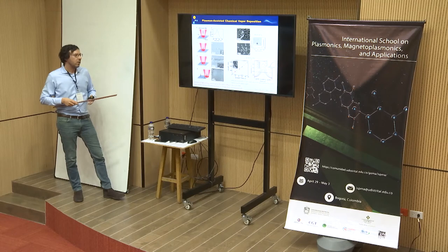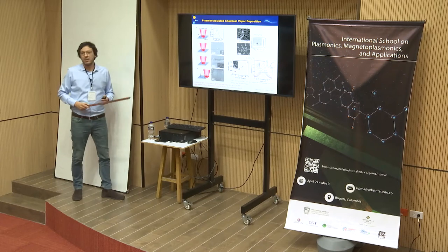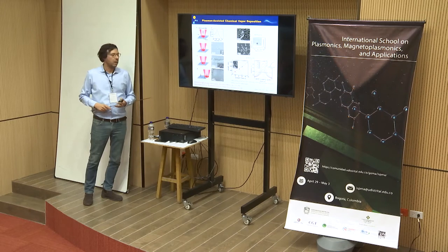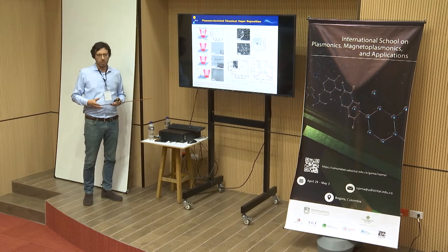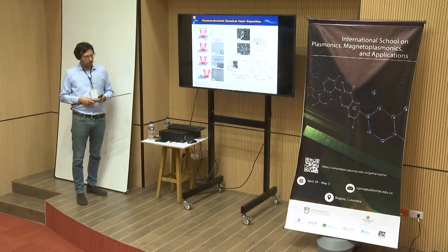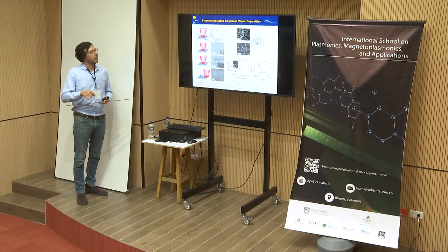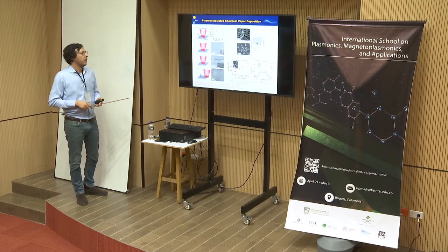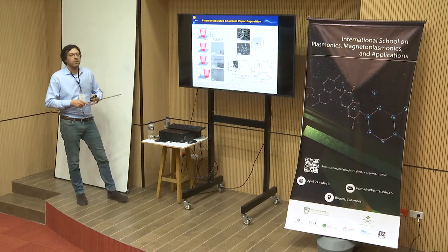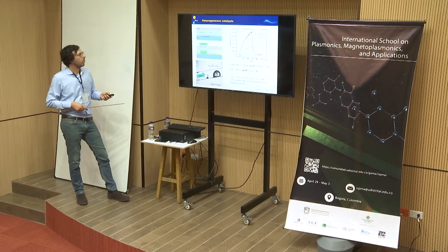And through some calculations, for example, they also show that you can use 10 to the fifth times lower energy than conventional processes. So this is what is really interesting about this phenomenon and this possibility of thermoplasmonics. You can just use the power which is needed for your laser, for your light source, to locally create a specific chemical process. Otherwise, with a thermal process, you have to heat up all your necessary setup to grow the nanostructures.